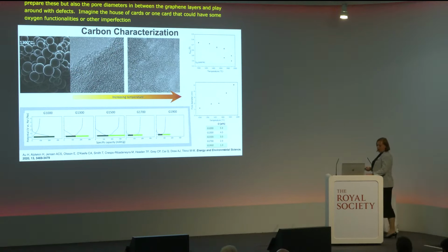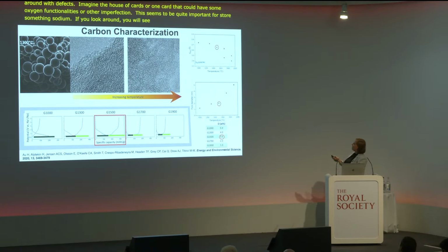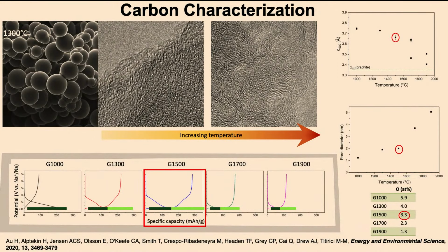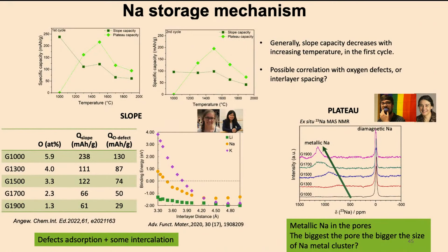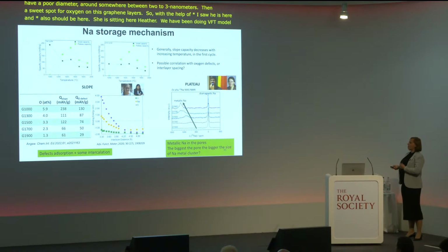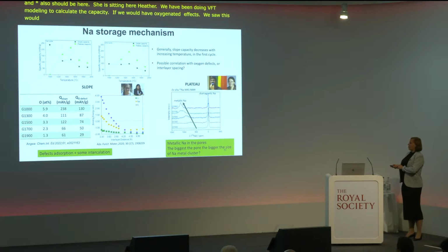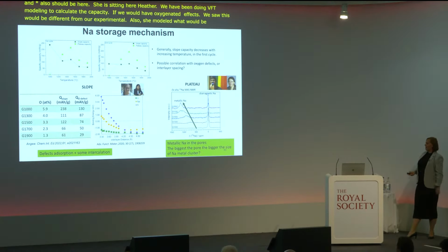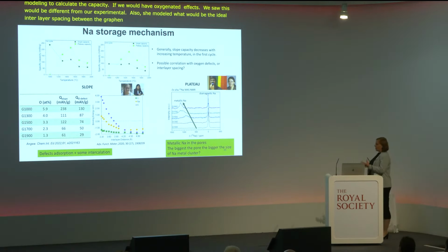If you look around, you would see that one situation performs the best, and this is when we have this particular interlayer spacing, close to 3.7 angstrom, a pore diameter somewhere between 2 to 3 nanometers, and then a sweet spot for oxygen on these graphene layers. With the help of Chang, I saw she's here, and Emilia, she should also be here. Yes, she's sitting there near Heather. We've been doing some DFT modeling to calculate the theoretical capacity if we would have oxygenated defects, and we saw that this would be different from our experimental results. She also modeled what would be the ideal interlayer spacing between these graphene layers for sodium to intercalate, and this seems to fit very well with our situation.